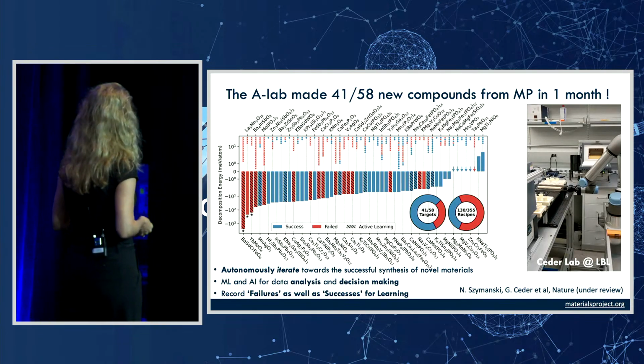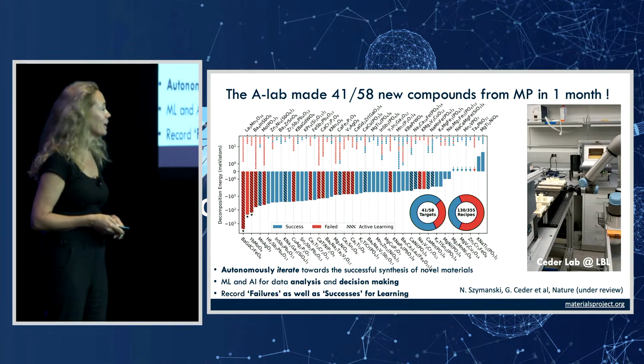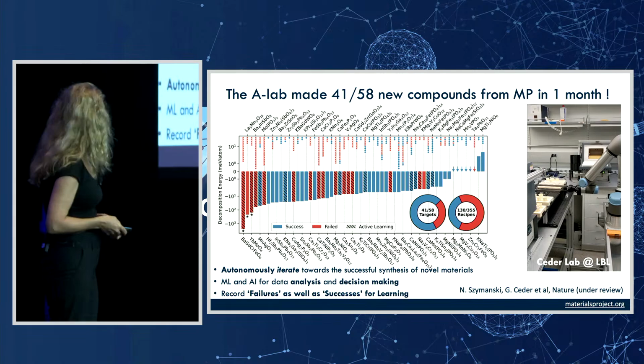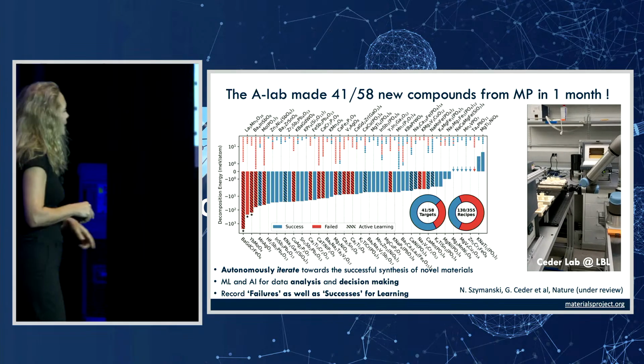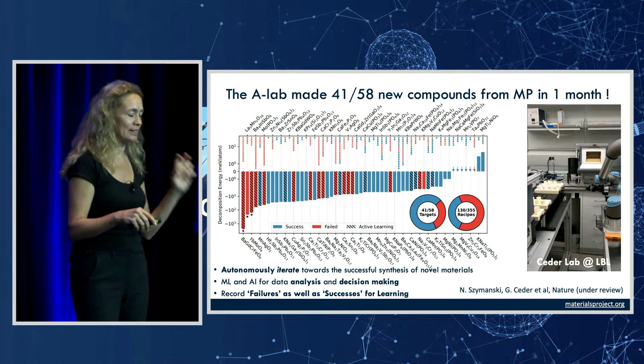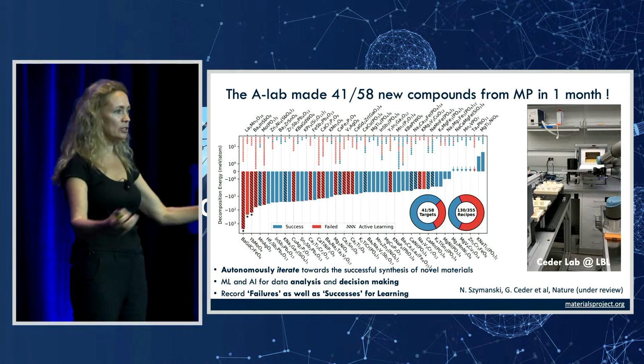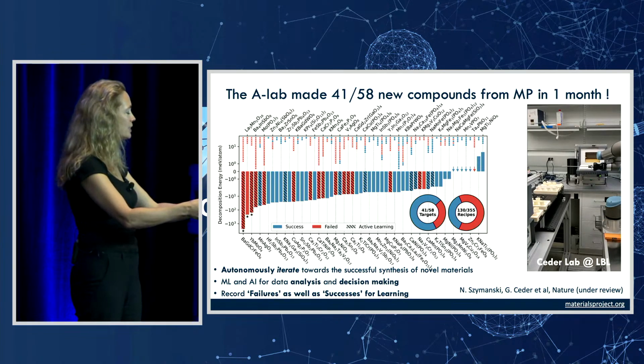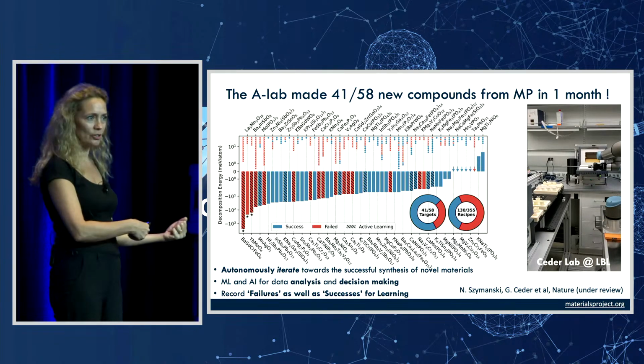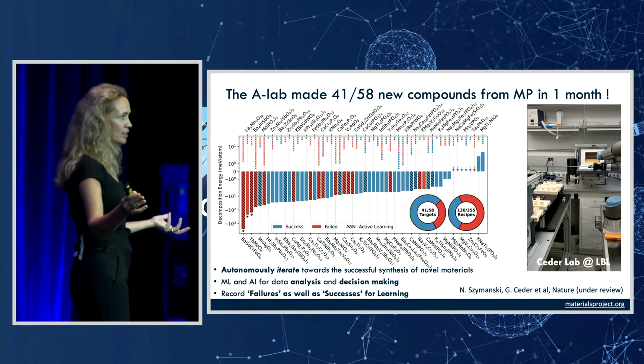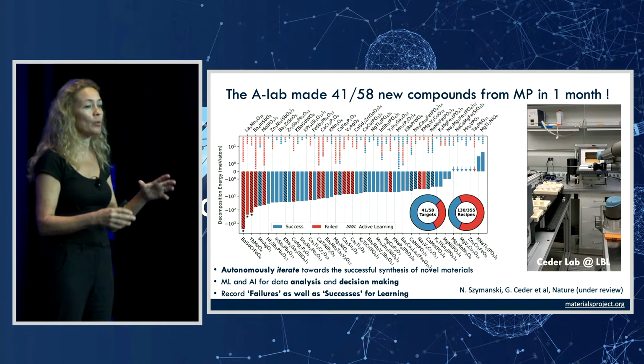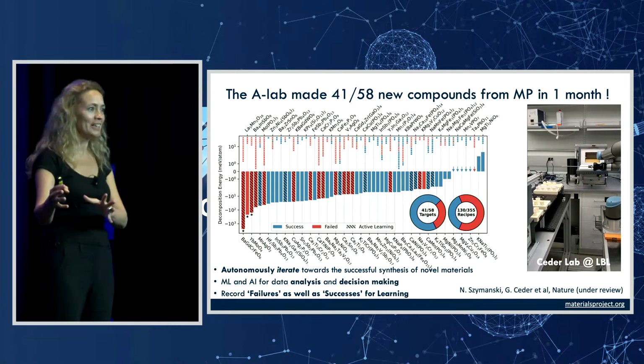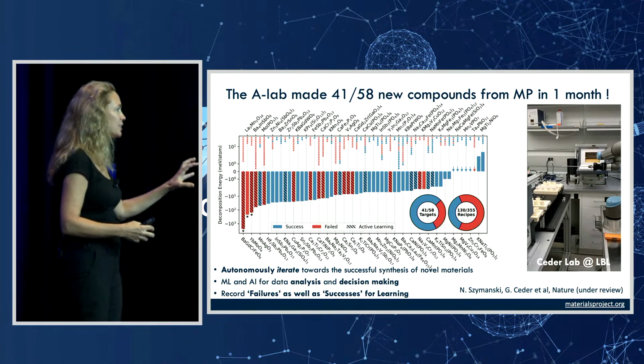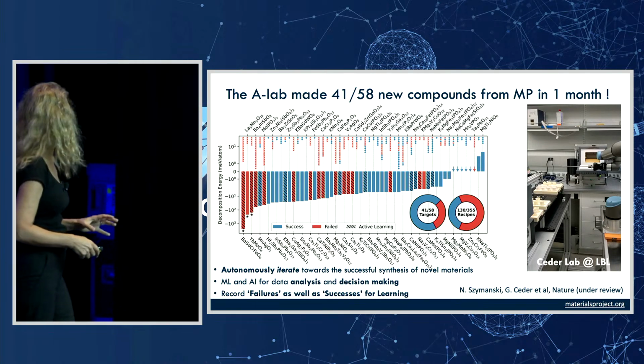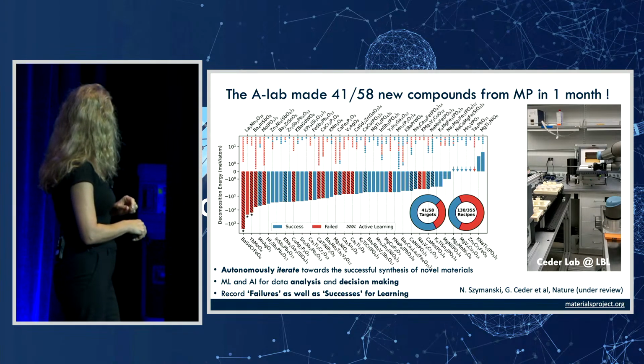And I really want to give a shout out to the Ceder group at Berkeley Lab that have partnered and built this wonderful A-Lab that literally is a bunch of robots going around and doing exactly what a graduate student would do. They take precursors, they mix them, they grind them up, they put it into furnaces, they take them out of the furnace, they put it into the XRD, they do a rapid scan with the XRD, then they use machine learning algorithms to figure out where the accurate XRD sample is from, so I can learn more and specifically identify what we made. It is a beautiful example of automated synthesis and characterization. It talks directly to the Materials Project.